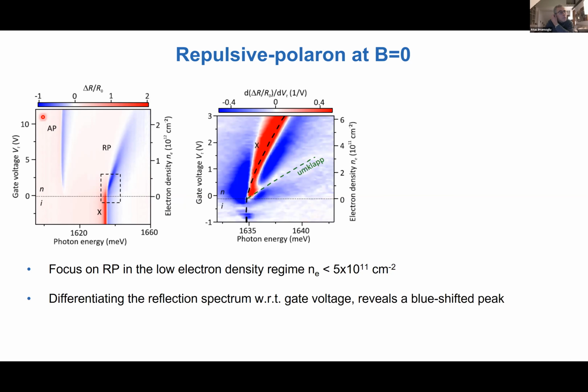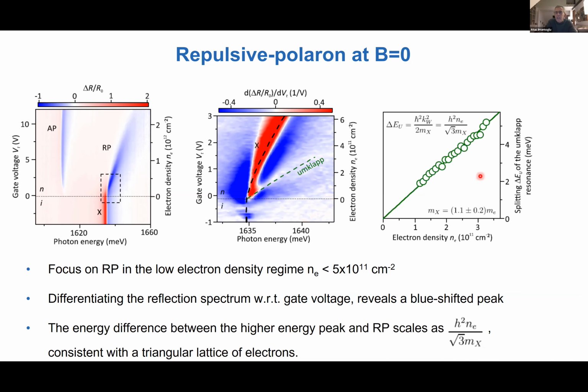Okay, but if we look at it more carefully, and we do so by differentiating the reflectivity with respect to the gate voltage, such that we are more sensitive to the changes in the electron density, then we see that in addition to the exciton line, we have a new resonance, which is this umklapp resonance that I was trying to explain. Okay, so it's much weaker than the exciton resonance. But what is important is that its energy splitting at any given electron density scales with the electron density. And the proportionality constant is precisely what we expect based on the exciton mass, and the rest is just the factors that arise from the triangular lattice.